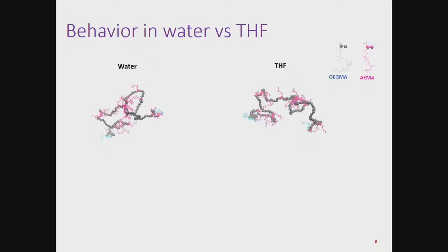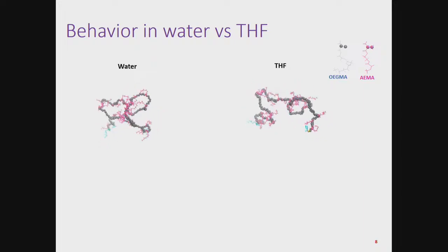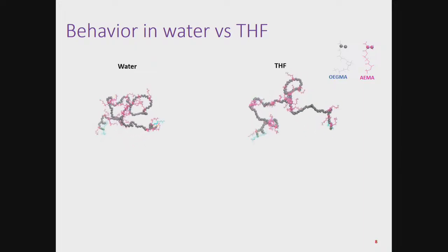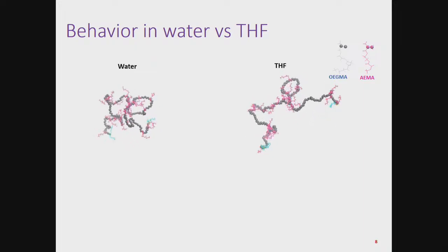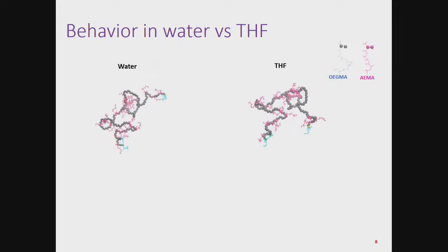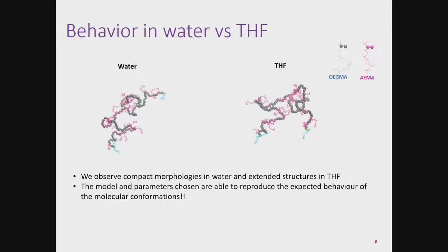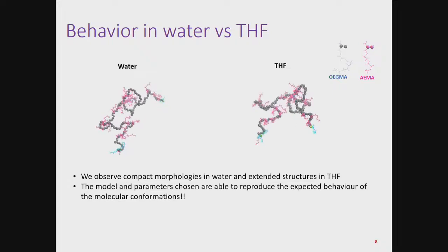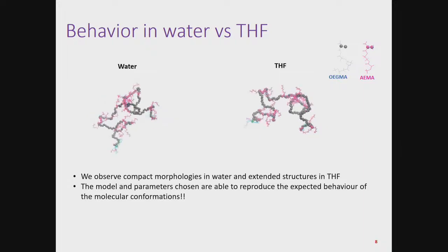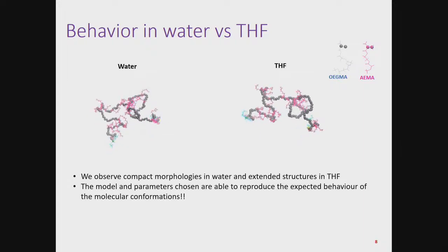Here you see the structure in water, and here you see it in THF, which is a good solvent. As the simulation progresses, in THF the structure opens up as compared to water. We will also quantify these observations, but from the simulation snapshots or movies, what you observe is that in water the morphology looks a bit compact as compared to THF. We see extended conformations here. That is the observation right now. We will be quantifying them in a minute.